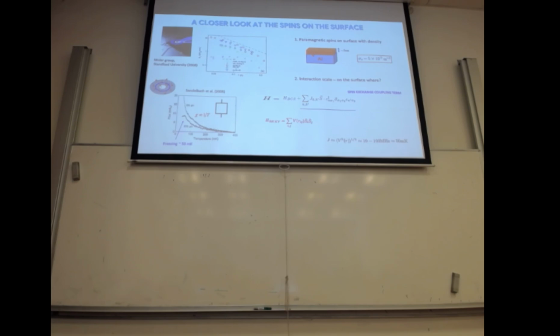the typical value of this RKKY that you have for the aluminium, you put in the features of the aluminium, and basically you come up with an interaction between the spins that is comparable. So in this old paper that we did, we were quite happy because physically we were understanding that this flux noise could be due to interaction mediated by RKKY.